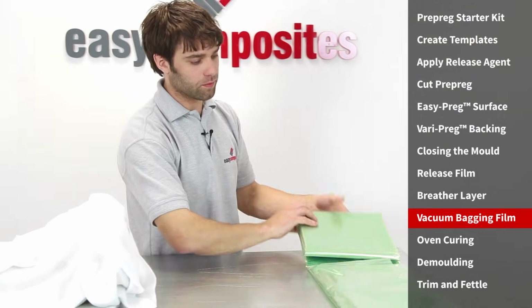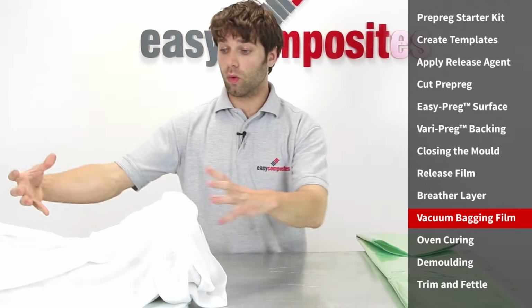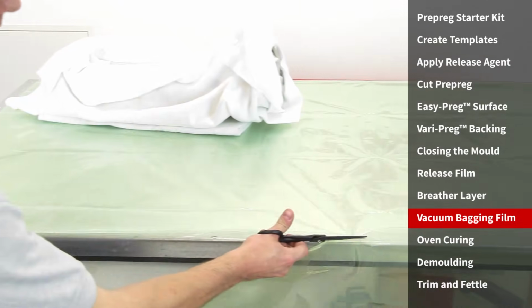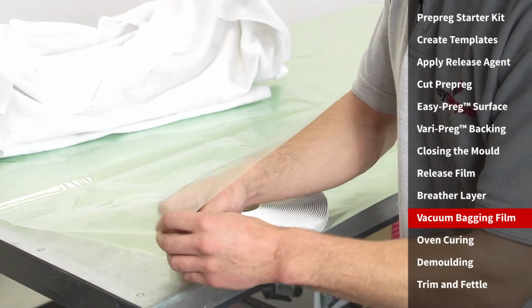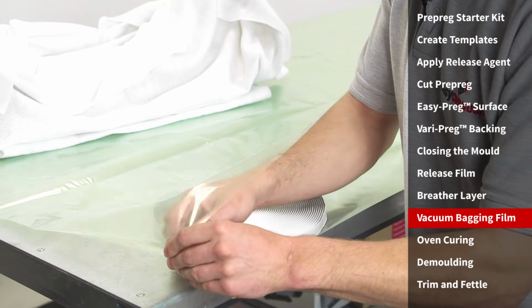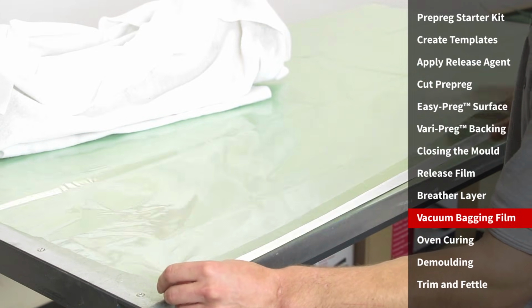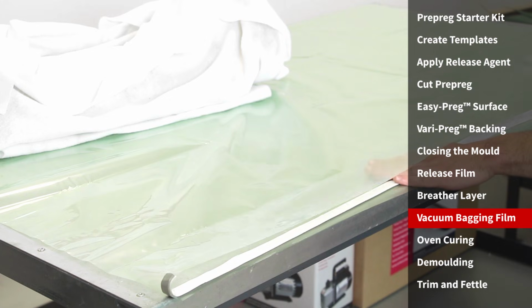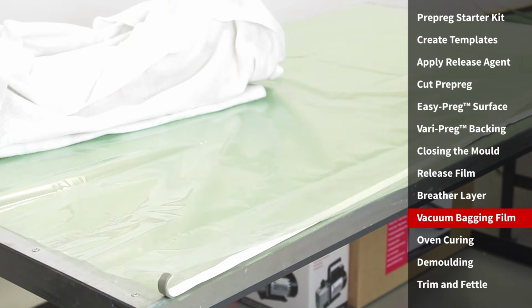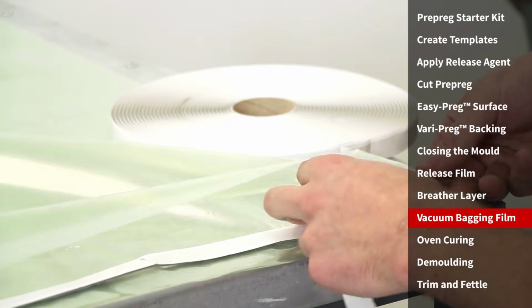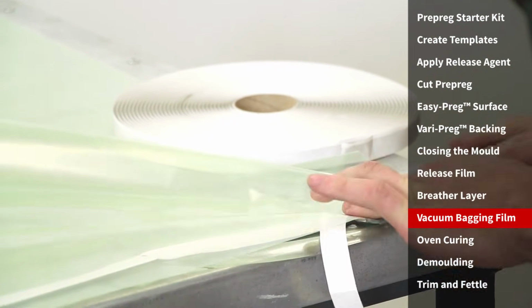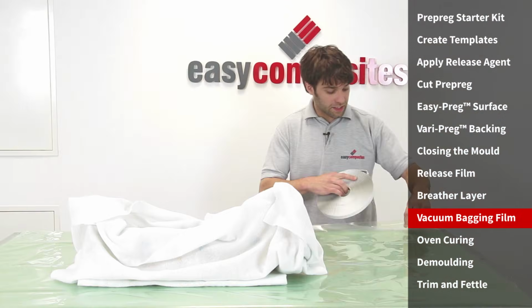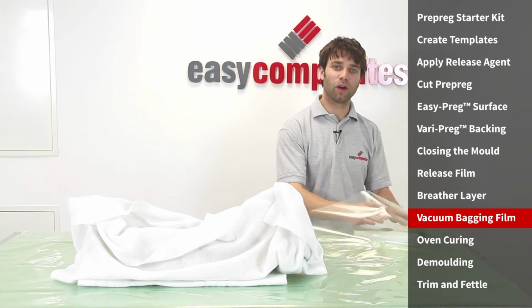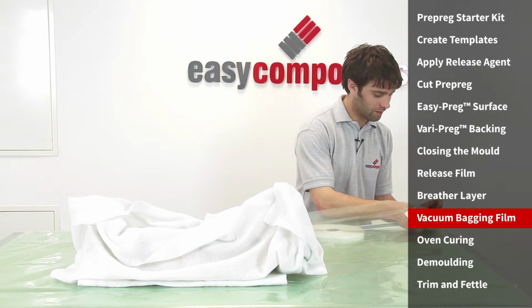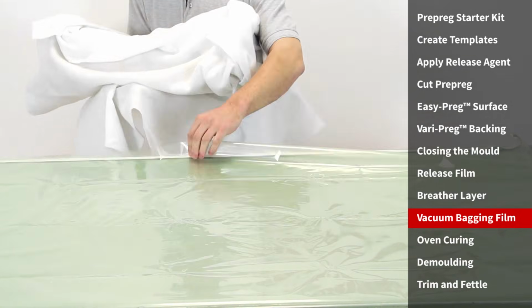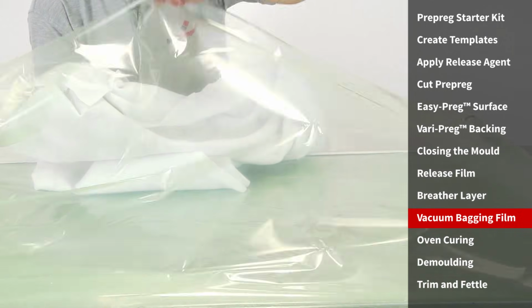Now we're going to use the vacuum bagging film from the kit to make an envelope bag, so a bag that all of this goes inside, and seal it. To seal the bag, you want to go slightly beyond the fold in the film, and then lay your sealant tape flat onto the bag. And then that fold, once the backing tape's been removed, can be doubled back on itself, and that'll provide a perfect seal. Makes life a lot easier if at this point you also apply the seal to the other side, but obviously don't seal the bag up completely. Lift the whole mould and the extra breather layer surrounding it into the vacuum bag.